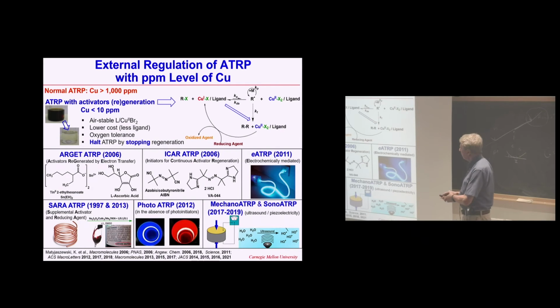And these can be chemical compounds. For example, ascorbic acid, can be also diazo compound or peroxide or tin octoate. You can have sulfides, which are used in food or wine preservation. You can have also a piece of copper or iron wire. You can plug in electricity and control it either galvanostatically or potentiostatically. You can use light, you can use mechanical forces, typically generating a piezoelectric system. However, very important is that if you stop incorporating this reducing agent, if you stop feeding ascorbic acid to a system, the reaction would stop nearly instantaneously.